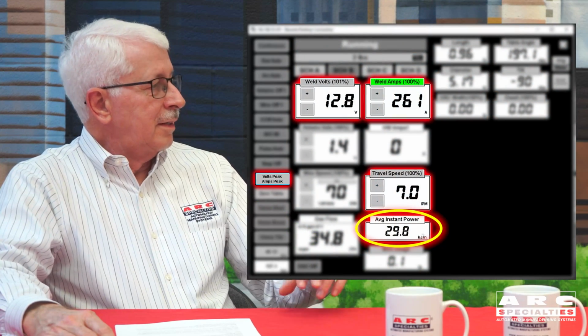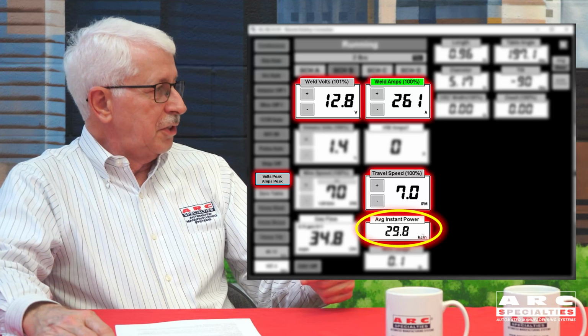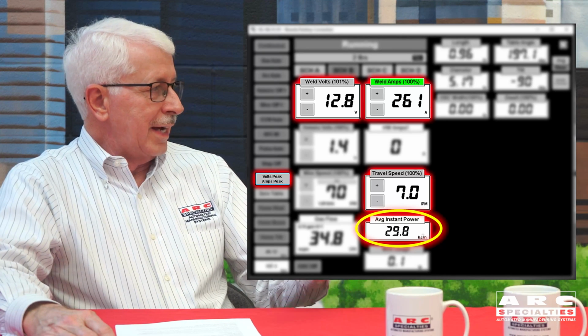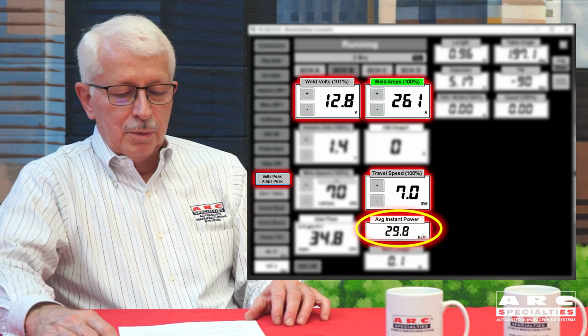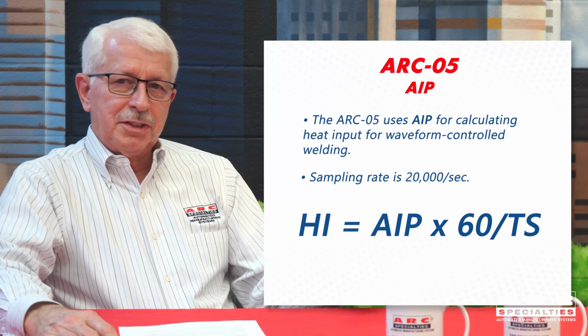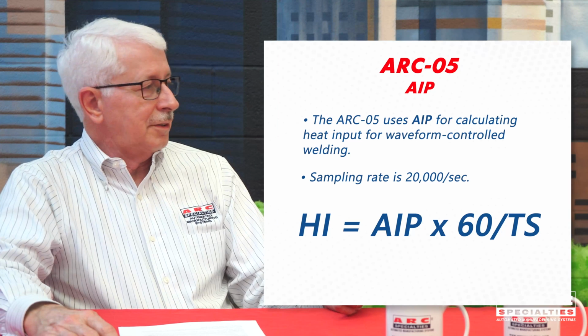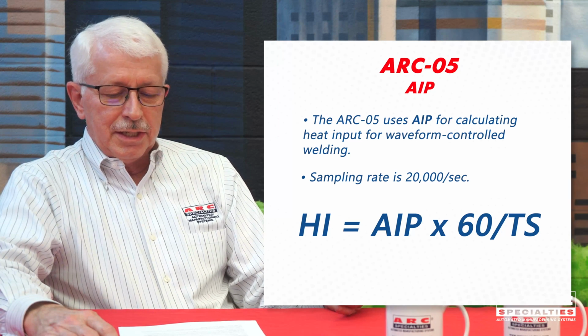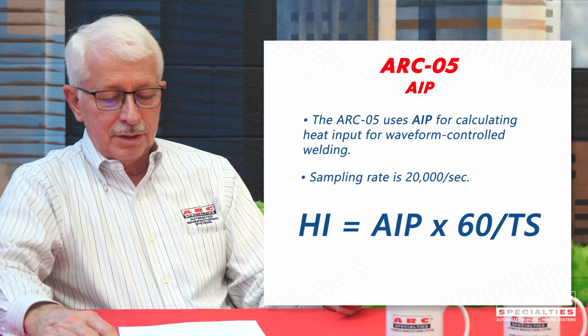Well, I've had people ask the question, if my customer insists upon having average instantaneous power, can you give that to me? Well, yes, we can. We've added that into the ARC-05 control. And so if you hit the heat input button, it will toggle from this conventional heat input to AIP, or average instantaneous power. And the way that works, as Dick mentioned, you have to sample at least 5,000 times a second. And in this case, we're actually reading at 20,000 times a second.